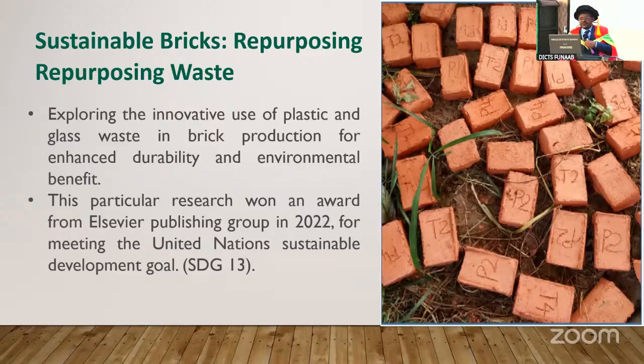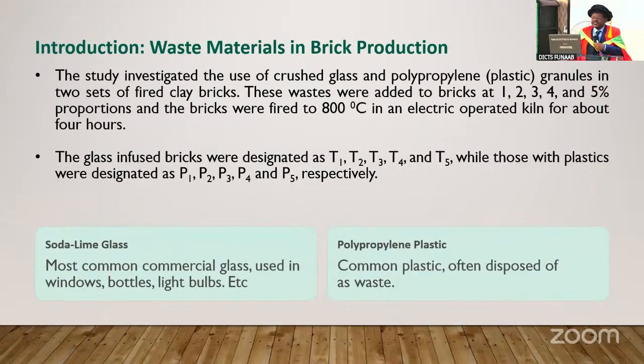The introduction, waste material in brick production. The study investigated the use of crushed glass and polypropylene, that is plastic granules, in 2 sets of fire clay bricks. These wastes were added to bricks at 1, 2, 3, 4, and 5% proportion, and the bricks were fired to 800 degrees Celsius in an electric operated kiln for about 4 hours. The glass infused bricks were designated T1, T2, T3, T4, T5, while those with plastic were designated P1, P2, P3, P4, and P5 respectively.